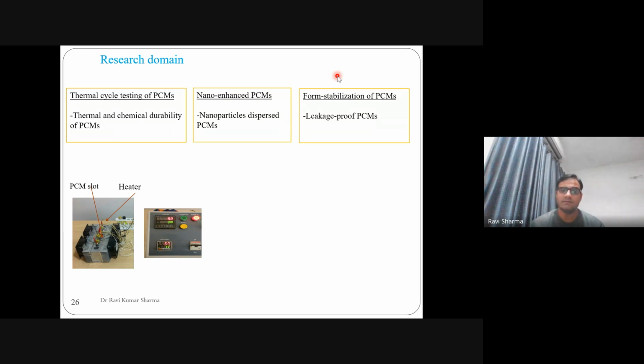This was the tester that we had developed, and we still use it. We can use it for infinite time, where this machine doesn't stop and doesn't require any human intervention. Once you turn this on, it will work on its own for a thousand cycles, for 10,000 cycles. The maximum it can be used for is 99,999 cycles, after which it becomes 1 lakh, a 6-digit value, but this machine has been set up to 5 digits only. So in one shot, I can use it for 99,999 times of melt and freeze for a single PCM.